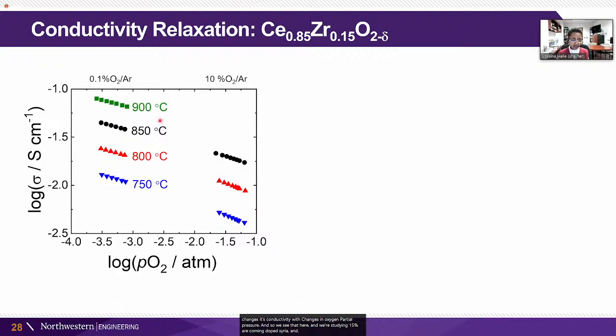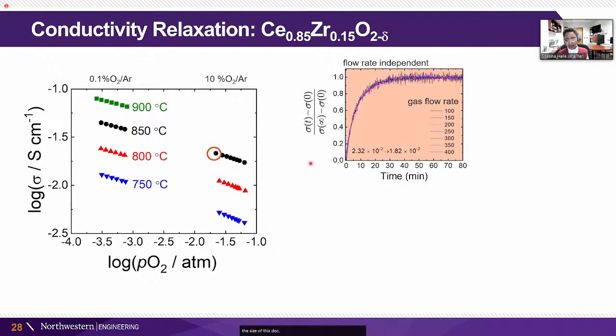And we just have two different ranges that we can access given the gas compositions that we're using. And so we're going to now do step changes within these individual regions. So we do a step change where we change the oxygen partial pressure to such a small amount that you wouldn't be able to see it within the size of this dot. And the normalized change in conductivity looks like that.